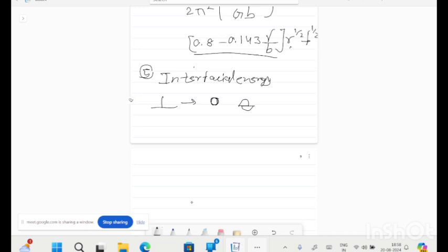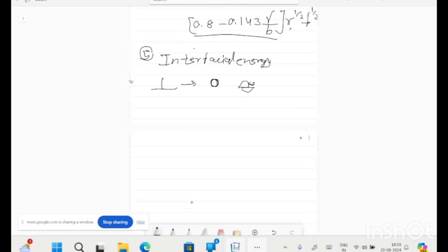In the sheared particle, the extra step formed results in an increase of interfacial energy of the precipitate, meaning the step increases the surface area, so it increases the interfacial energy. This increase in interfacial energy must be supplied by the applied stress.